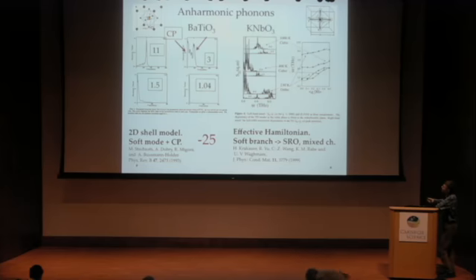And we see that originally one band, one soft mode, seems to develop some complicated structure, like a new, what we would call a central peak, and this central peak became extremely sharp at the phase transition. So actually, the original soft mode picture changed to a picture of order-disorder dynamics jumping between different sites in the model. And there is a first shell model calculation for potassium niobate showing something similar. Here, however, we don't see the developing of the central mode. We see just one mode, which is broad, but softening down. And what was pointed out here was that actually there is a whole branch of modes which is softening. But still, we don't see the central peak.